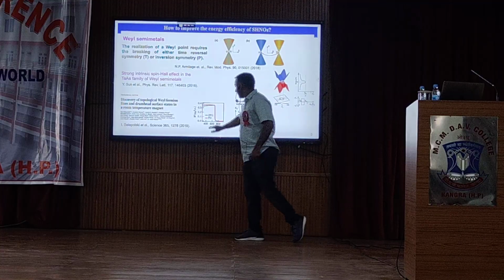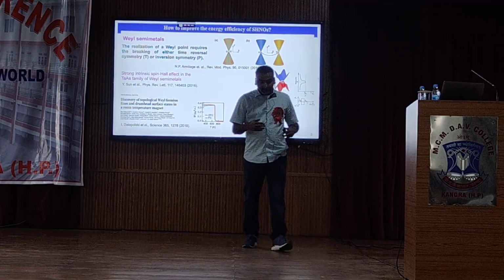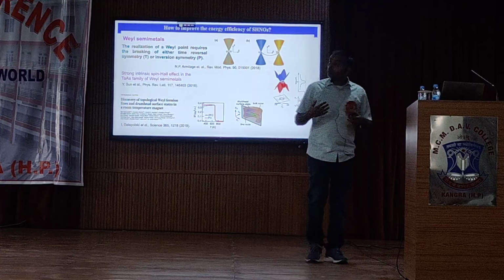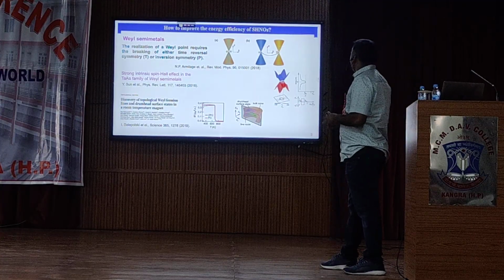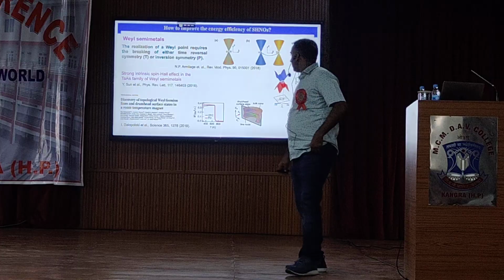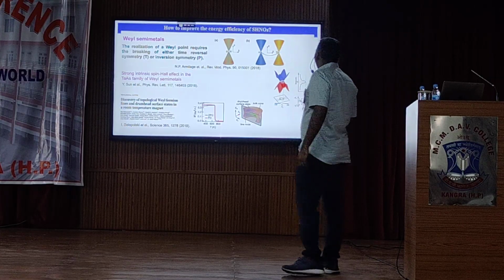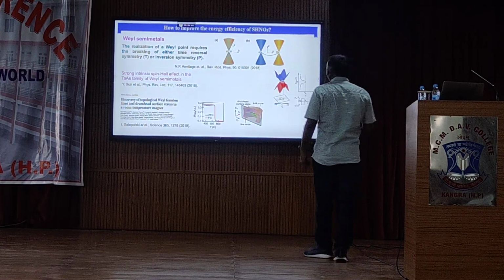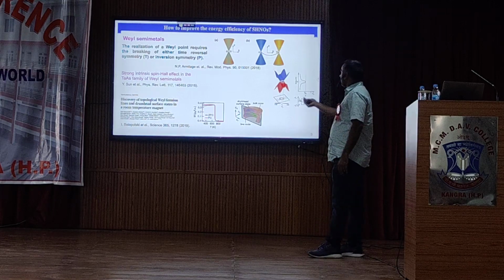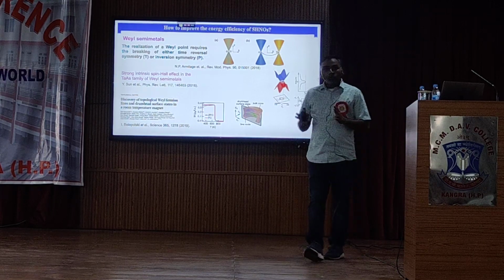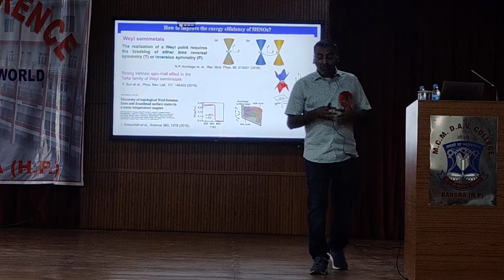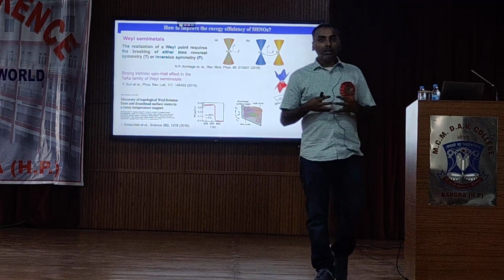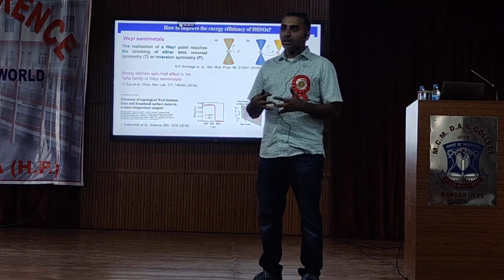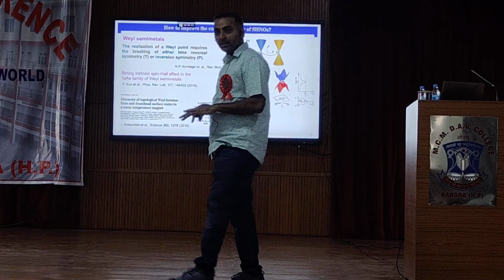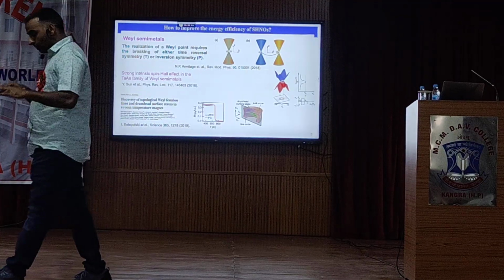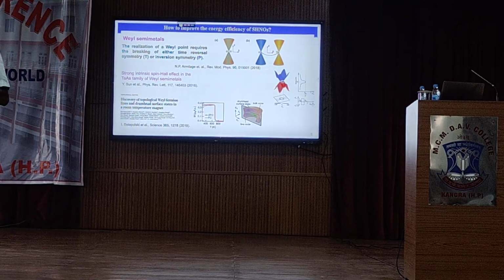And this material, which we are interested in for our experimental work, was experimentally grown first at Princeton University in 2019. It is a Heusler alloy, cobalt two manganese gallium. This material also shows interesting topological features. So we are interested in materials like this. We want to use these materials in our devices, but we cannot use them in bulk form. First, we need to get thin films of these materials, because our device scales are in the nanometer range. First, we need to grow the films in the nanometer range, which is quite small.